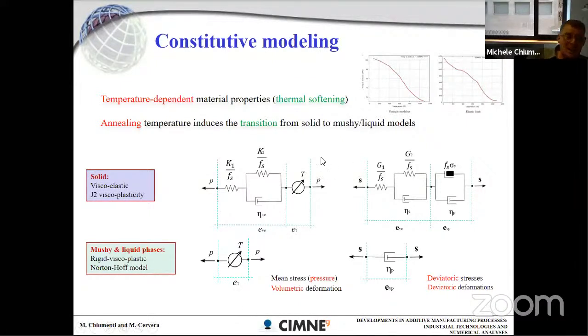Typically, when the material is solid, we have a viscoelastic, viscoplastic model. And this means that you have elasticity. Well, here you can see the elasticity term and the viscosity term. But what is more important, you have a viscoplastic behavior. So you have this damper in parallel with the plasticity. And what happens when you switch to the mushy or liquid phase, you want to represent your material as a liquid, as a viscous liquid. And typically what you want is to represent it through a purely Norton-Hoff model. So on the volumetric side, you have just thermal deformation, but the deviatoric part of the stress is represented just by a damper. Typically, it is a non-linear Norton-Hoff, which behaves as a rigid viscoplastic material.